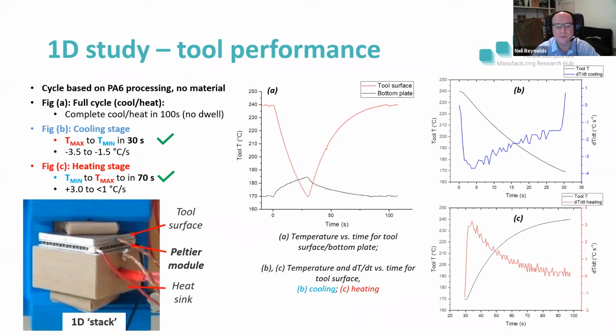So the middle graph shows temperature versus time at the tool surface and the rear plate, and you can see that we can get down to and back up again in about 100 seconds, which is very encouraging. It's faster than the existing variothermal technology we've been evaluating. On the right hand side, that shows us the actual cooling and heating rates. So in blue, the cooling rate shown on the right hand side of the right hand graph, going down to about minus 3.5 degrees a second.